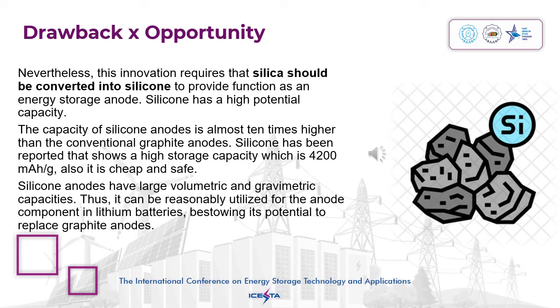Silicon has been reported to show a high storage capacity of 4,200 milliampere hours per gram. Also, it is cheap and safe. Silicon anodes have large volumetric and gravimetric capacities. Thus, it can reasonably be utilized as an anode component in lithium batteries, giving it the potential to replace graphite anodes.